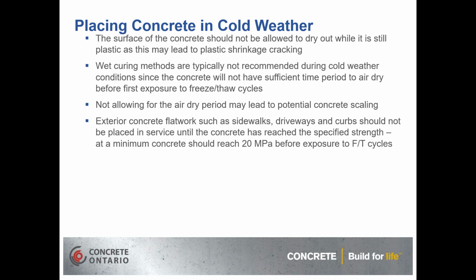Very common in the residential market, exterior concrete flatwork such as sidewalks, driveways, and curbs should not be placed in service until the concrete has reached a specified strength. At a minimum, if you have to place it in service, the recommended strength that the concrete needs to reach is 20 MPa before exposure to freeze-thaw cycles. What happens with these types of elements in the residential market is that the mechanical abrasion of snow plows in the winter, trying to clear the snow off the sidewalks and the curbs before the concrete was able to achieve a specified strength, can result in significant damage to the concrete surface.